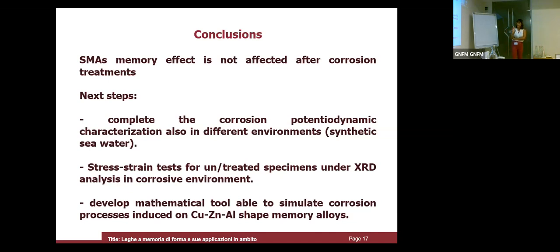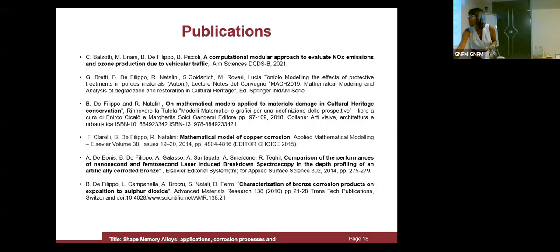So to put our sample under a stress-strain test in a corrosive environment under XRD analysis, because it's important to have a characterization to better understand the behavior of our alloys in particular conditions. At the same time, to perform XRD, because the stress-strain causes a variation in the peaks of austenite and martensite, in the ratio between the peaks of austenite and martensite, and it's really interesting to consider in our future work. So, thank you for the attention.